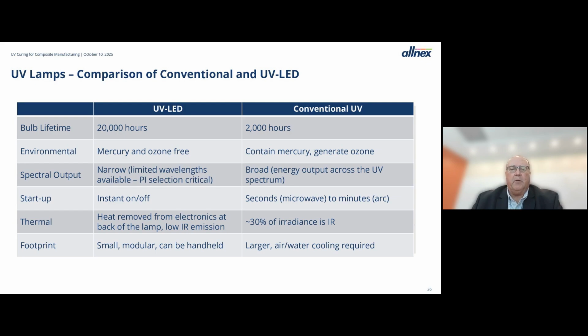So if we look at the comparison, with UV LED the bulb lifetime is many, many times as long as a conventional UV lamp. They are mercury and ozone free, but they have very narrow output. So your PI selection is critical. UV LEDs, because they're electronic, instantly start when you flip the switch. Conventional UV takes a few seconds to get to full power. As I mentioned, conventional UV puts out heat out the front of the lamp, and UV LED does not. And UV LEDs are generally small, modular, and can be handheld, so they're easy to manipulate on a line or in a handheld configuration.